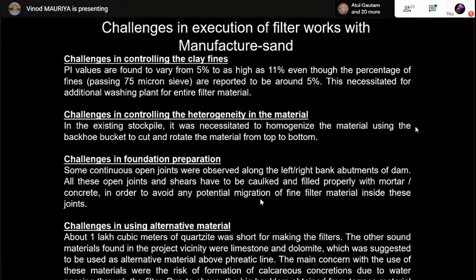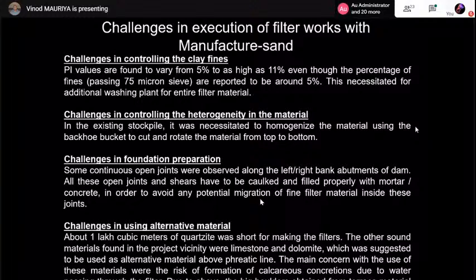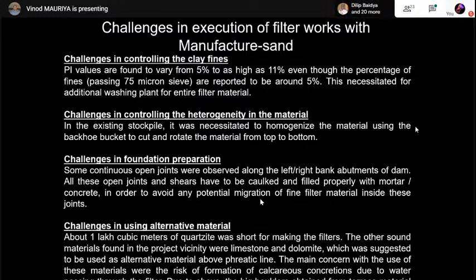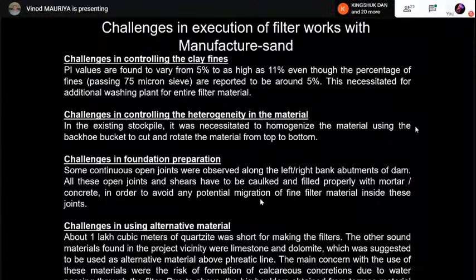The next challenge was the heterogeneity. There was a lot of heterogeneity in the quarry itself. So at the stockpile, we mixed properly to provide a homogenized material as a filter material. The next challenge was during execution, during the foundation preparation, a lot of continuous open joints were observed in the dam body. So those open joints and the shears were caulked and filled properly with the mortar concrete in order to avoid any potential migration of the fine material inside these joints.